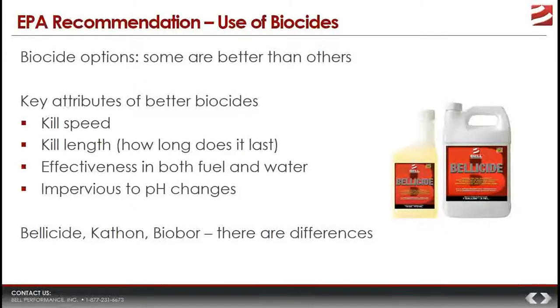And that means that there are plenty of biocide chemistries that are less effective that only maintain a kill rate for 1 to 2 weeks. And that is no good compared to 4 weeks. So kill speed, kill length, effectiveness in both fuel and water. Typically, you will add a biocide to the fuel portion, and it will kill microbes that it comes in contact with, but it will migrate to the interface between the water and the fuel, and then it will cross that interface. As it crosses that interface, it's now, of course, entering into the water phase.